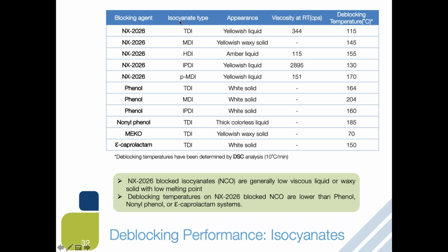So we basically blocked monomeric isocyanate with this blocking agent, and those block system tend to have increased viscosity, especially phenols and nonylphenol. Those guys tend to turn solid, whereas NX 2026 block, especially when you look at the TDI, has shown very low viscosity, viscous liquid, in comparison to, let's say, phenol being solid, nonylphenol being very thick viscous liquid, and then MEKO and the caprolactam. When you look at the deblocking temperature comparison, NX 2026 has shown lower or comparable deblocking temperature when you compare to phenols and nonylphenol and caprolactam.